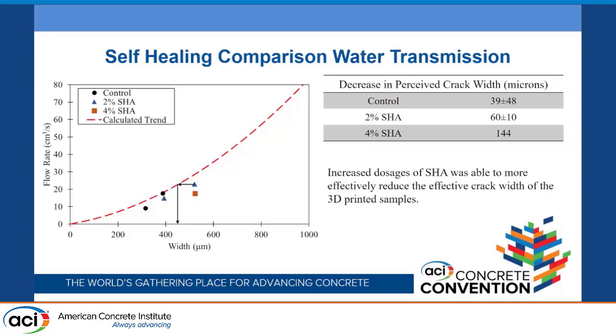For these samples, we saw that our control was essentially negligible, hovering slightly positive but inside the range of error. Our 2% was a little bit more effective, and our 4% was even more effective than that. Just as you'd expect, increasing self-healing agent dosage will increase your effective healing, notably not completing self-healing entirely, though.